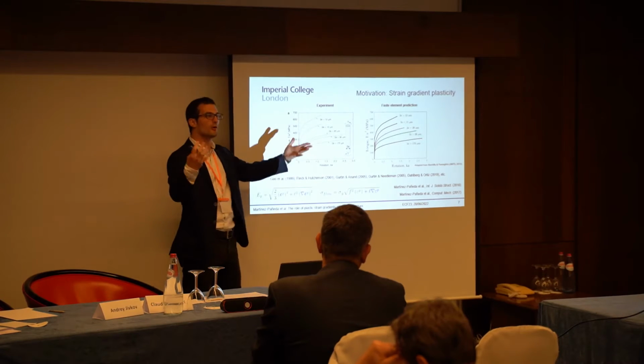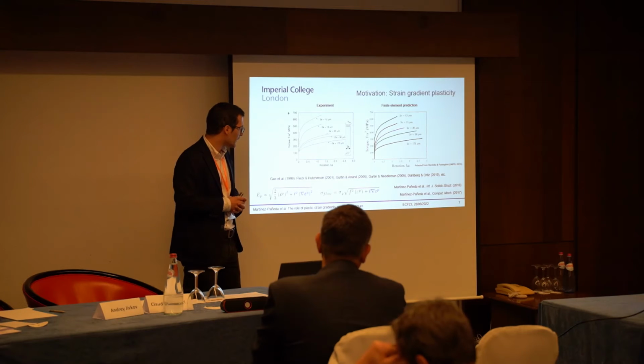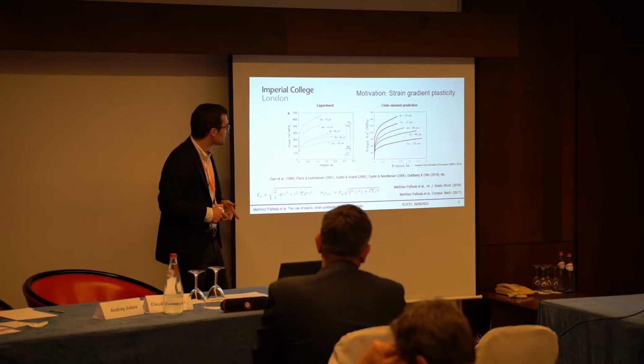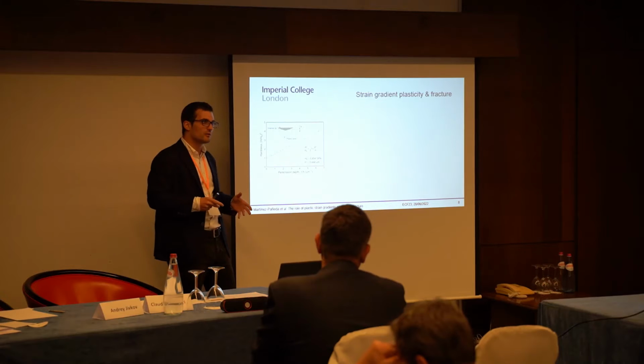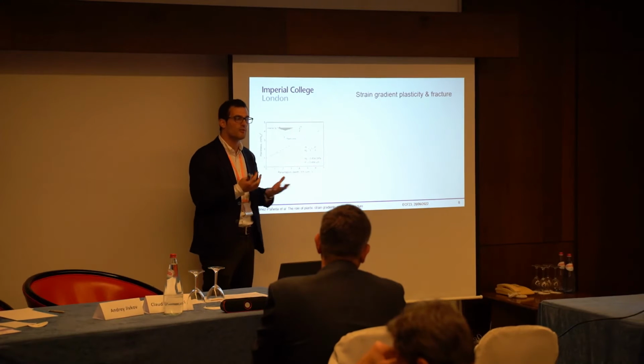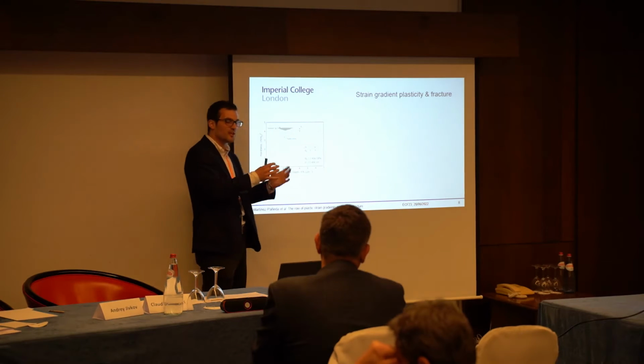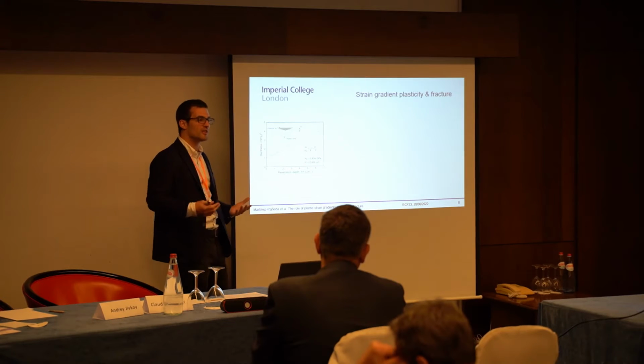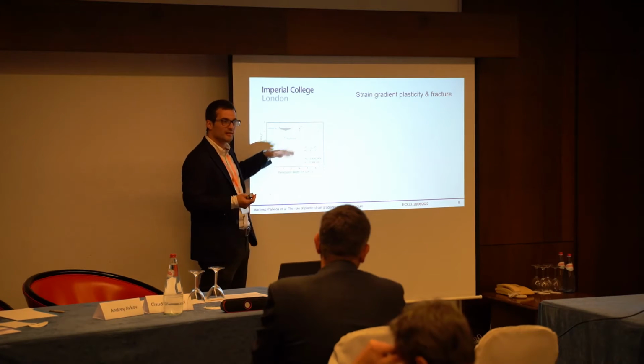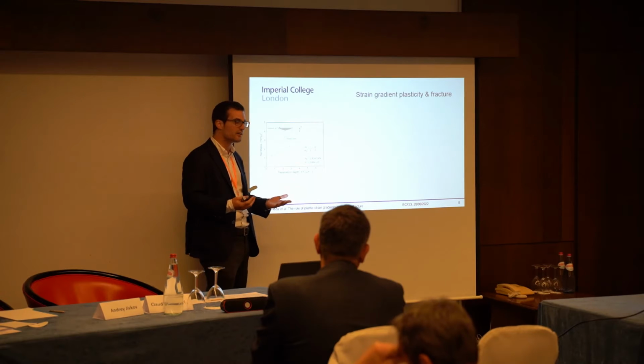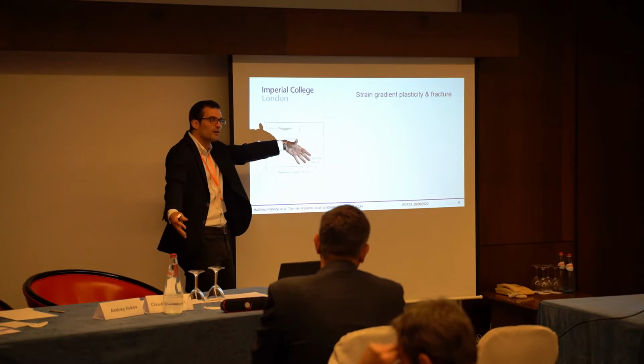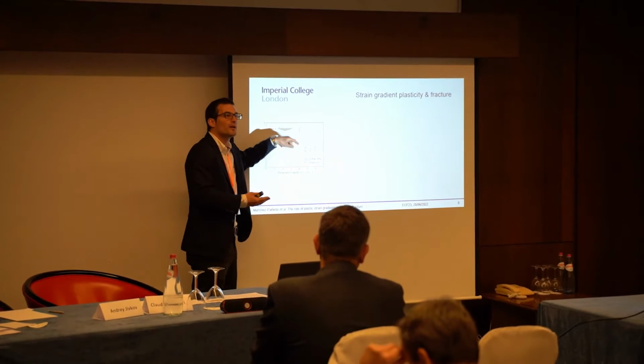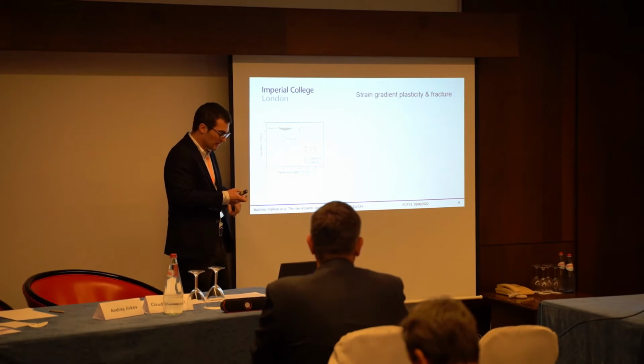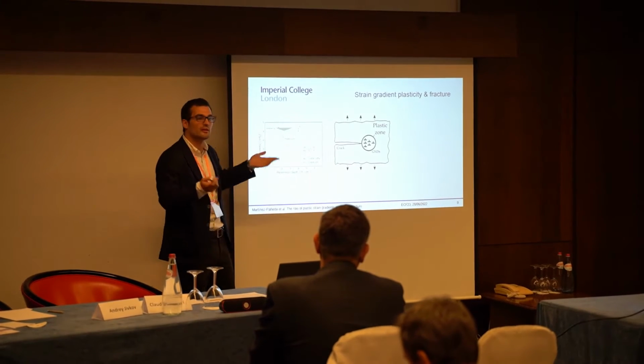This smaller-is-stronger effect, this inverse of plastic strain gradients. And one thing that I should emphasize here is that the length scale that is relevant is the size of the plastic zone. It's not the size of the sample. In this case, we're constraining the plastic zone with the size of the sample, but if you look at, for example, indentation, you again see a very strong size effect. Even though you are indenting a very large sample, it's just that plasticity is quite localized. You have it near the indenter. So it's the same thing as you would see in cracks, right?